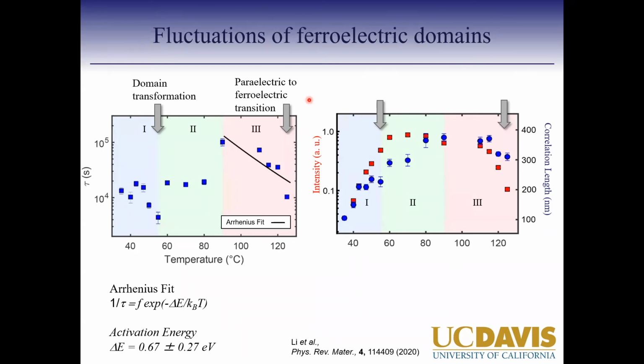Some of our guesses: it could be related to oxygen vacancy motion in these materials, where oxygen vacancies moving around could cause slight changes in the polarization, which we then see as these domain fluctuations. The activation energy we estimated from our fits is about 0.67 eV, and the activation energy for oxygen ion motion is about 0.8 to 0.9 eV, so a similar order. Another theory, proposed by another group, is that there are some topological defects present in the system which move around, and I'm not sure what they mean by that.